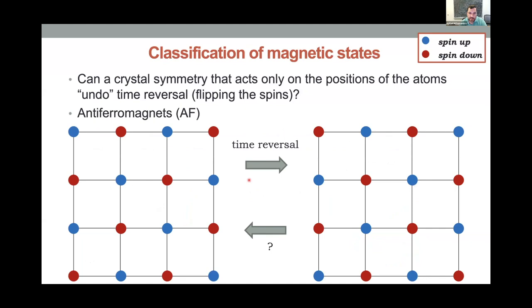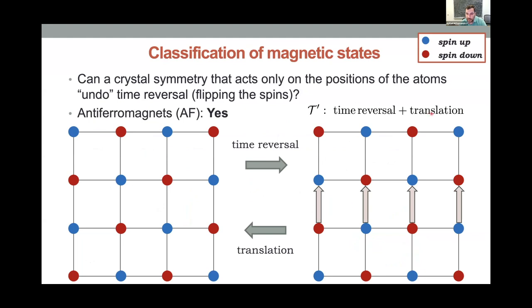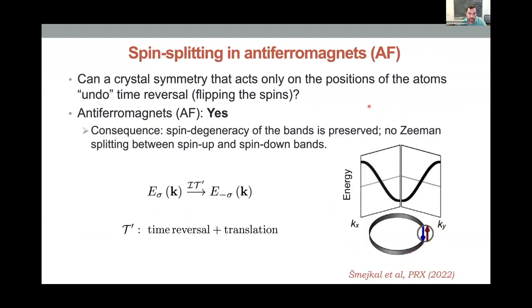Now, in an antiferromagnet, the situation is different, because if I flip the spins, blue goes to red, red goes to blue, it's clear that if I do a translation by a unit vector, by lattice vector, I'm sorry, I recover the same magnetic configuration from which I started. So T prime, which is just time reversal plus translation, is a symmetry. And because T prime does not, because translation does not affect momentum, you still have the condition satisfied for a spin degenerate band. So even though you have long-range magnetic order, you do not split the bands.